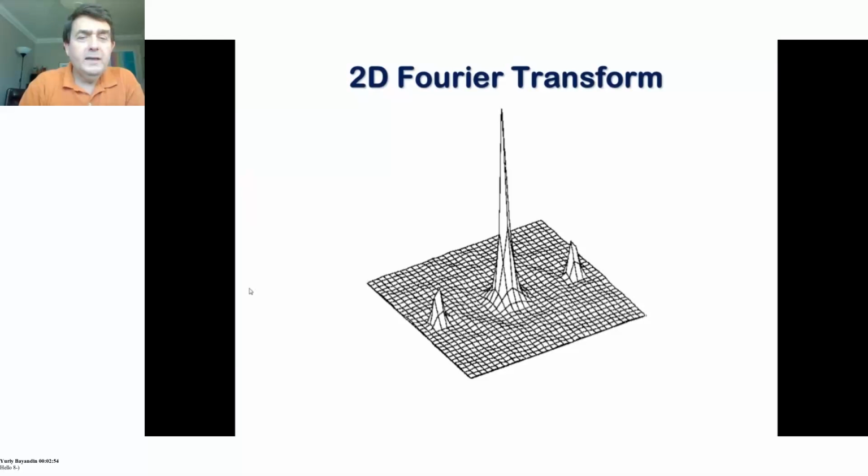A warning here: this type of technique does not give you any independent idea of the direction of motion. It only gives you the magnitude and the line direction upon which that motion happened. It doesn't tell you if it's going forwards or backwards, but it tells you along that line, this is the direction of motion. If you set the experiment up, generally you have a good idea what the direction of motion is going to be, so you bring some extra knowledge into that analysis.